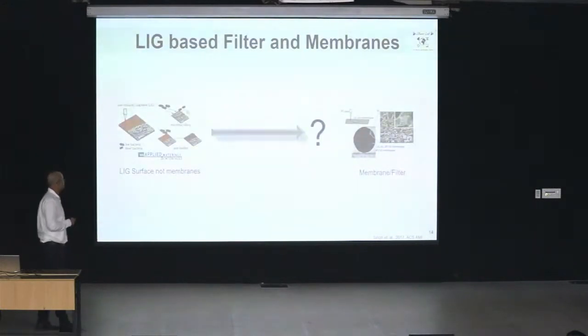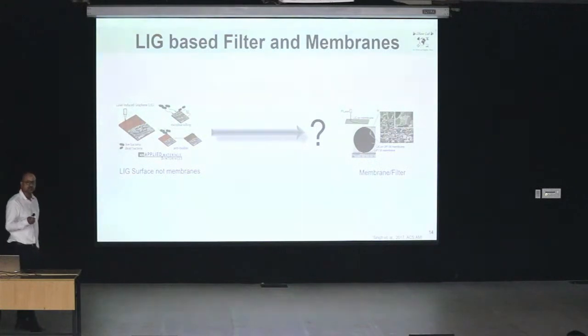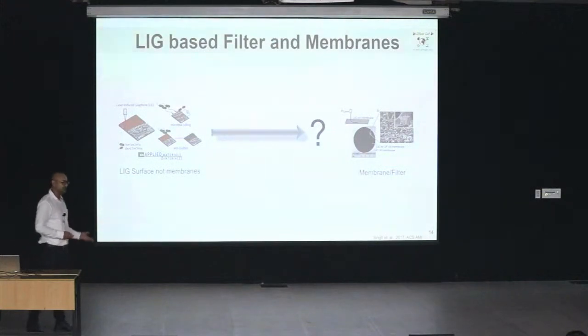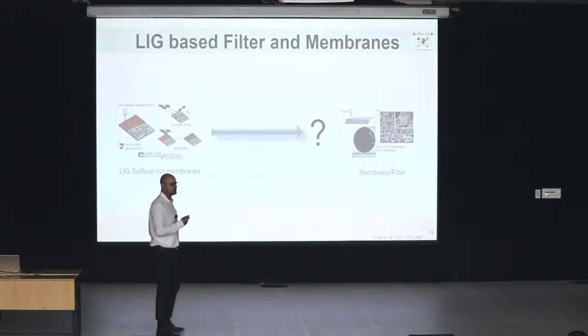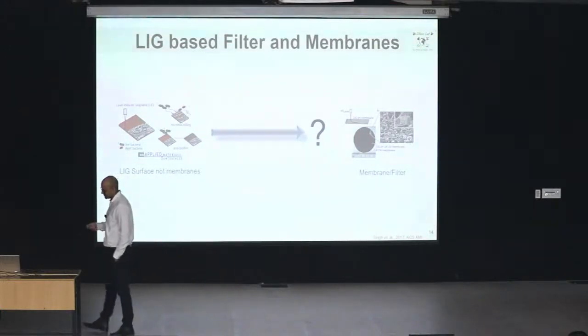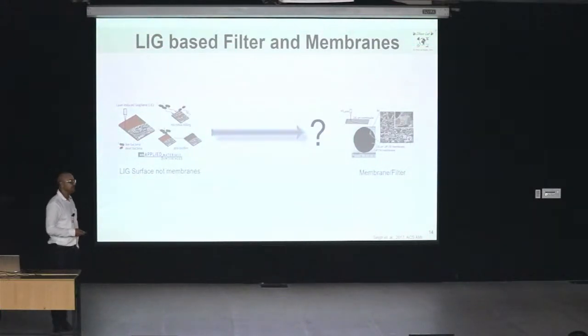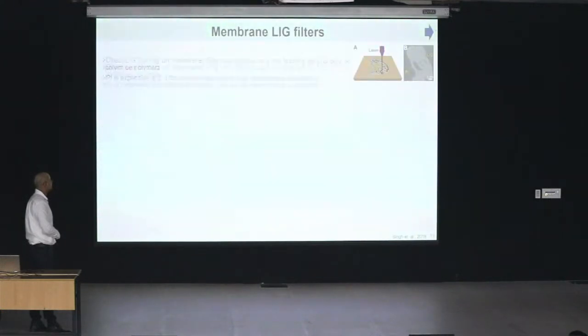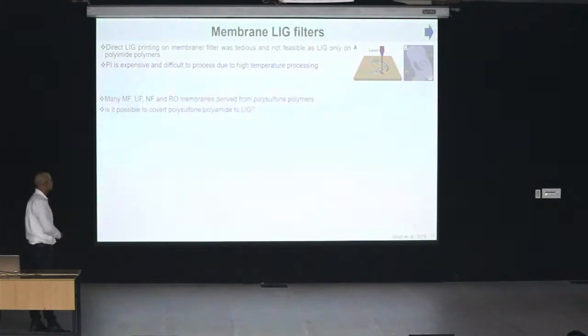So the idea was like, when this laser-induced graphene was invented, it was only made on a polyimide polymer, which is a very good class of thermally stable polymer. So the challenge was how we can convert these polymers to a membrane, because in membranes the most common polymers are polysulfone or other kinds of polysulfones and PVDF, and there are many, but polyimide was not in the list. So then the challenge was how we can make the laser-induced graphene on these membranes, for example polyether sulfone, because polyether sulfone is a highly used polymer.